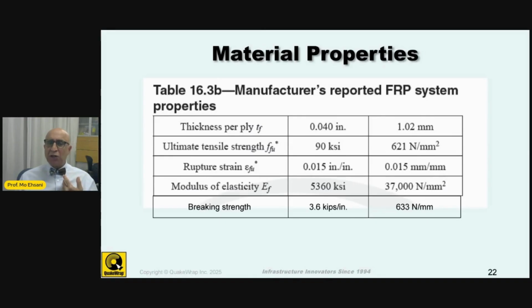And what I really like to use in most of my design is that I take that tensile strength, 90 ksi, and multiply it by the thickness of the laminate, and I look at the breaking force. In this example, this gives me 3.6 kip per inch. And that, as a designer, should give you a good rough idea of how this fabric would compare with, let's say, a number 4 or 5 or 6 rebar that you would be using in the field.